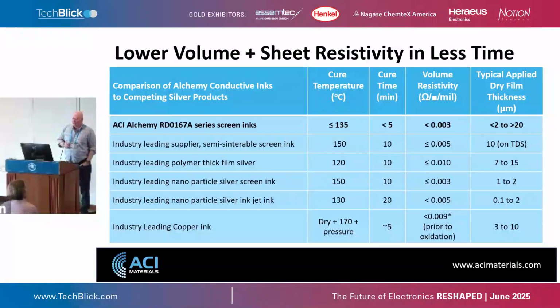So this is a look, and it's a little bit historical, at our Alchemy Ink series on top, curing at about 135 centigrade against other semi-sintering silver inks, against copper inks that require higher drying temperatures and some compression to get their conductivity. And it's really about getting that cure time down to use tunnel dryers and roll-to-roll dryers that are much shorter. So you really want a dwell time of 1 to 2 minutes.